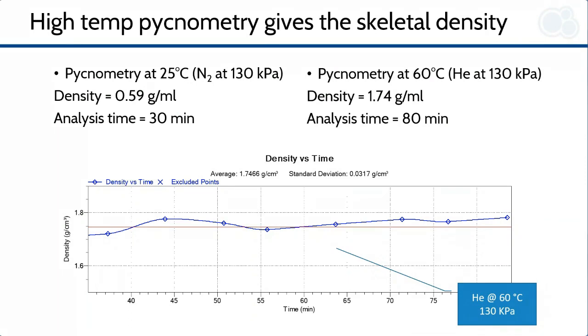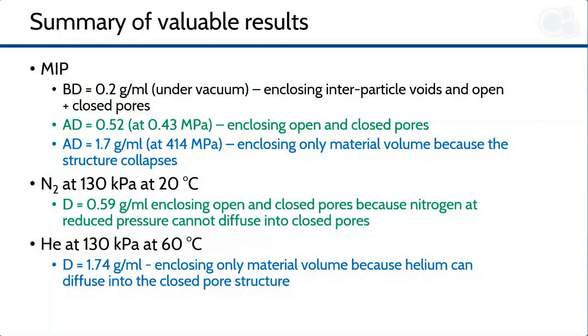a closed structure. At this point we can say that on the instant coffee under examination, mercury porosimetry provides reliable information about particle size, bulk density enclosing all open, closed and interparticle voids, envelope and apparent densities calculated at different pressures, and the closed pore volume. Nitrogen pycnometry at reduced pressure measures rapidly the envelope density relevant to the open porosity and enclosing the inaccessible voids. Helium pycnometry at reduced pressure and high temperature measures the skeletal density because in these conditions helium can diffuse completely